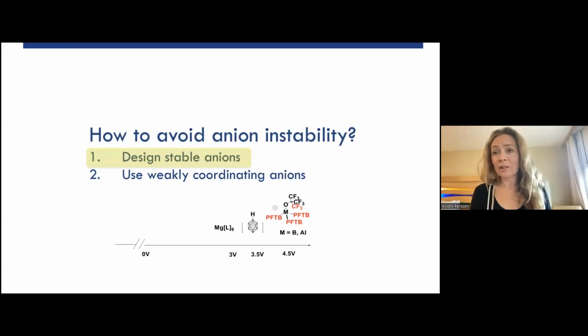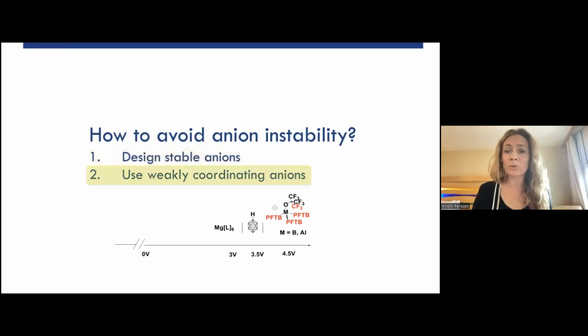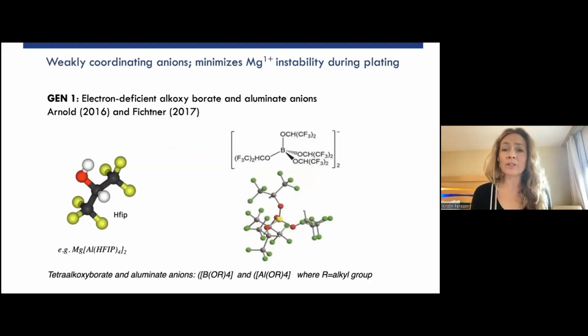But there is another design metric out there, which the community suggested. What if I design a highly weakly coordinating anion that doesn't hang out with magnesium much at all? Then I should be able to stay away during that difficult plating situation and maybe I'll stay stable. So the use of weakly coordinating anions took an interest. And I think the first versions of this came from Arnold and Fichtner, who suggested these electron-deficient alkoxy borate and aluminate anions. We can see a picture here. You have the borate center or aluminum center and these beautiful, highly fluorinated ligands, in this case two CF3 groups coordinated to each arm of the ligand. They show that these work quite well with magnesium metal, not perfectly, but quite well, and also increase the electrochemical window.